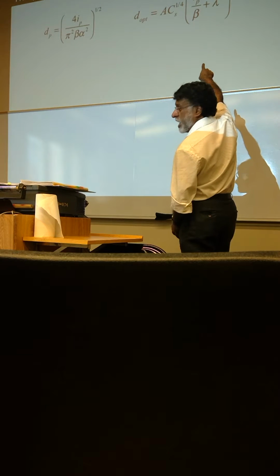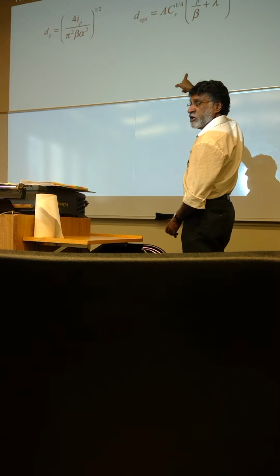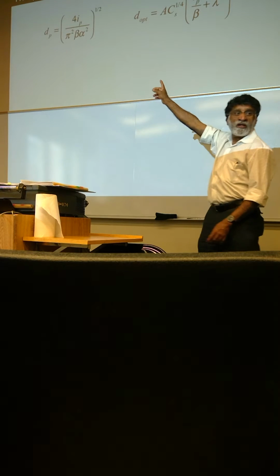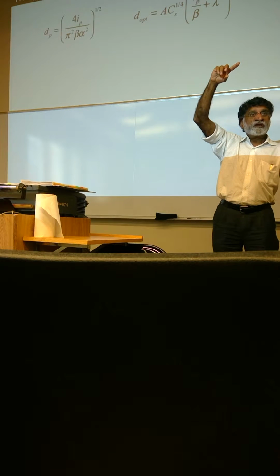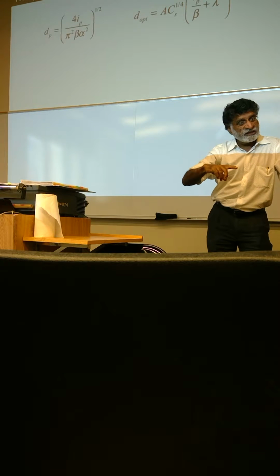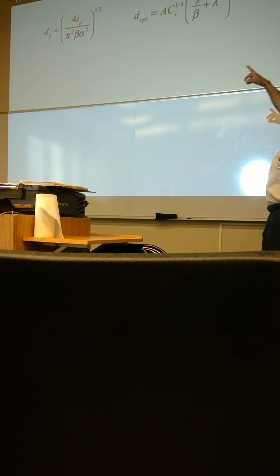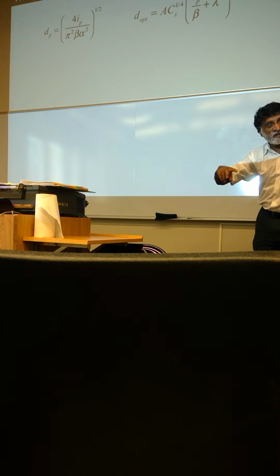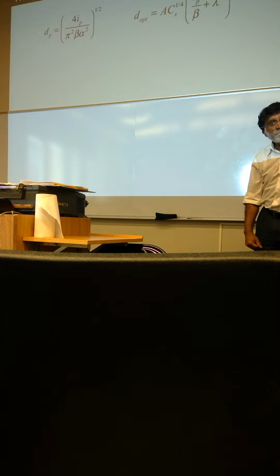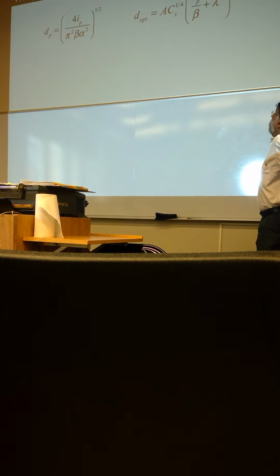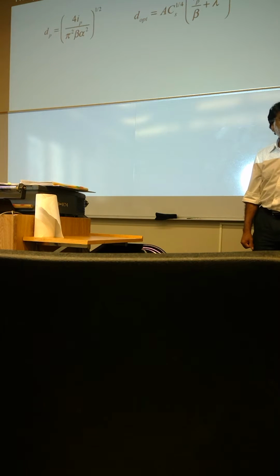So if you change the acceleration voltage, if you increase the acceleration voltage, what will happen to the wavelength lambda? It reduces. So you can see that by increasing that, you can get better spatial resolution. What was A and C again? A and C are constants. CS is the aberration, the spherical aberration correction factor.